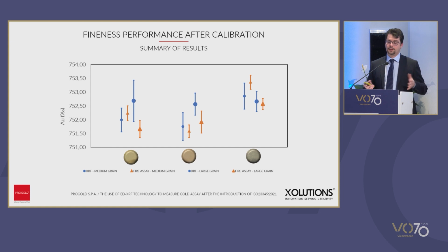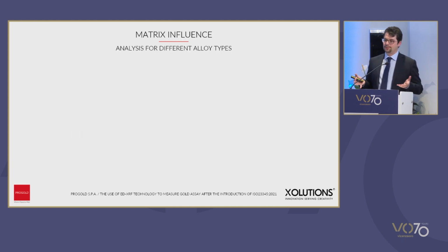that into consideration. Here you see a diagram of what I just said, and you see that apart from the first case of yellow gold, there is always a good correspondence between the fineness achieved with the fire assay and with X-ray. So the performance of this technique for the alloys considered and for these measurements is very good. Now, let's have a look at other parameters.